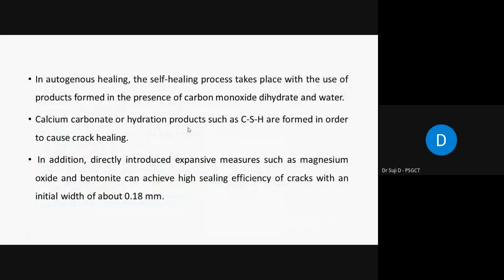So in autogenous healing, the self-healing process takes place with the use of products formed in the presence of carbon dioxide and water. And calcium silicate hydrate is our hydrated gel, which is formed due to the hydration of unhydrated cement with water, right? In addition, expansive agents such as magnesium oxide, and sometimes bentonite clay, can also be directly introduced in order to achieve high sealing efficiency of cracks with an initial width of about 0.18 mm. So if you have micro cracks of this range, definitely all these cracks will be autogenously healed by the natural healing process.